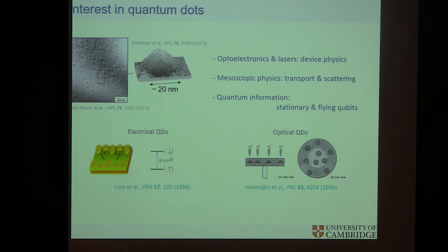That's why self-assembled quantum dots, these guys, possess the actual bulk properties of their host materials, the indium arsenide and the gallium arsenide. So the lattice structure that we know from bulk actually still is sustained, and therefore optical properties kind of have those properties carried forward. But they're roughly 20 nanometers in diameter and about 2 to 3 nanometers in height. So they're like small pancakes, little disks that are on top of the surface.